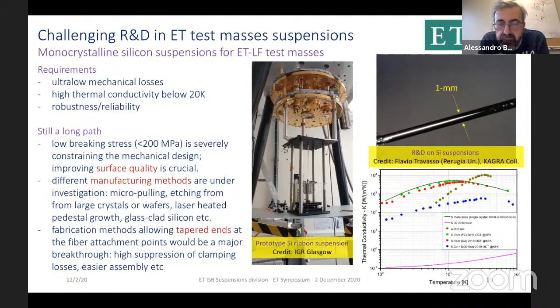I would just like to cite two of the R&D works that are ongoing at the moment. This is at Glasgow. They're testing a short ribbon suspension to see how it works at low temperature. And then the group of Perugia, in collaboration with KAGRA, are testing round suspension structures. They're measuring the thermal properties, breaking stress, etc. It's already nice to see that thermal conductivity figures in these thin fibers, already in the prototypes made so far, approach the bulk thermal conductivity of silicon. This is good news, I think. So at least that aspect seems not to be too critical.